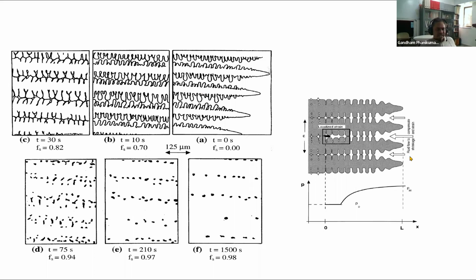Now, fine microstructure of a dendrite is more likely when you have a higher speed. Experimentally, we have also observed that if you have slightly higher speed, then the solidification cracks in aluminum alloys have been avoided. So that is our practical experience. That way, the microstructure starts to play a role in crack avoidance.